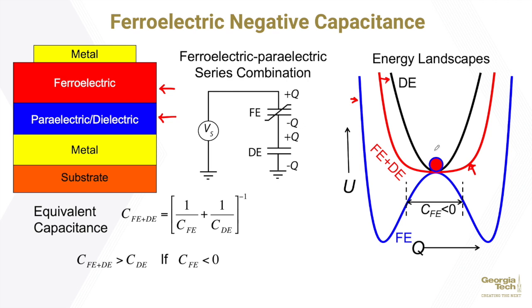Now, from a macroscopic point of view, what will be the signature that the ferroelectric material is actually stabilized in a negative capacitance state? To understand that, one can resort to the classic law of electrostatics, which says that if we have two capacitors in series, the total capacitance will be smaller than each of them. For example, if we take a 2 picofarad and 1 picofarad capacitor, then the total equivalent capacitance will be 2/3 of a picofarad, which is smaller than each of them.